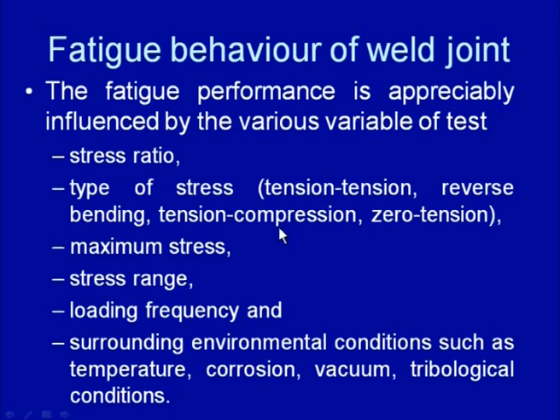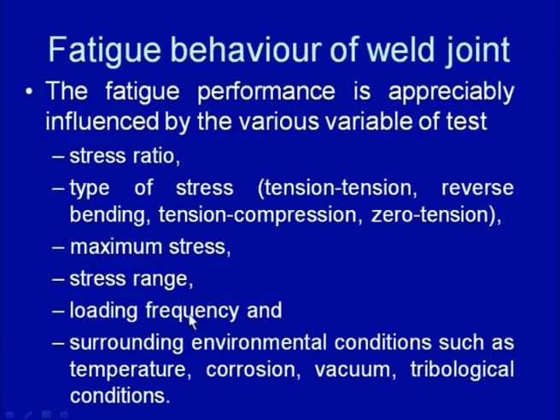Stress types used for conducting the test: it is tension to tension, meaning the stress varies from some minimum tensile value to a higher value, or reverse bending, or tension to compression, or 0 to tension. Then the maximum stress magnitude is identified, and the stress range is identified from the difference between the maximum and minimum stresses. Then the rate at which the load is applied is indicated as the loading frequency. Depending on the system, we can use a loading frequency of 5 hertz, 10 hertz, or 20 hertz, depending on the capability of the system being used for conducting the test.